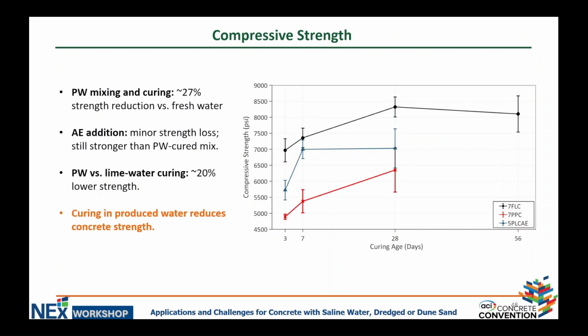In this slide, we can see again the black line, which represents the fresh reference mix, but this time compared to the two other mixes, the one that was made and cured in produced water and the 5,000 air-entraining admixture mix. We have two exciting things here. First is that the mix that was designed for only 5 KSI at 28 days actually reached 7,000 at 7 and 28 days, okay? But the other thing that is also very kind of impressive, or maybe actually bad, is that the mix that was made and cured in produced water has a 27% reduction in compressive strength.